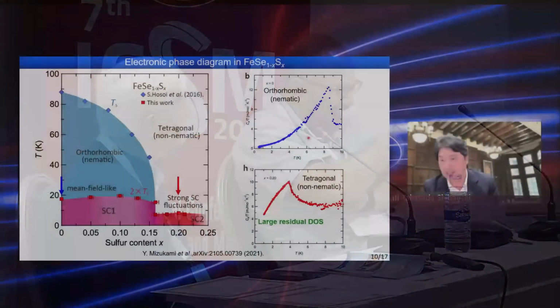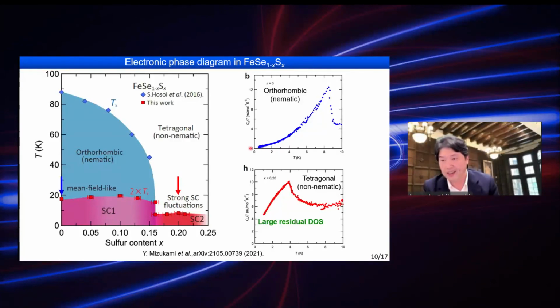Yes. Okay, so if you go back to the specific heat data, inside the nematic phase, we see this T-linear behavior at low temperatures. In the S-wave, fully gapped case, you should have exponentially small temperature dependence, but here we have T-linear behavior.